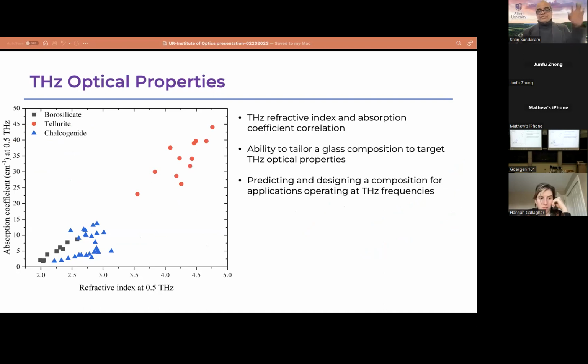So now I have plotted absorption coefficient versus refractive index for these glasses, and you can clearly see the clumping and grouping of these glass families. You can see here, at the left corner, you have the borosilicate and the chalcogenides, somewhat overlapping, but at the high end here, all the tellurite glasses are to the higher end of it. So obviously the tellurite glasses also contain rare earths, heavy elements, and high polarizability, and that's also tied to why we are measuring high refractive index in these frequencies.